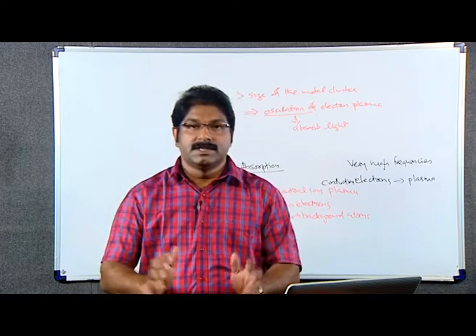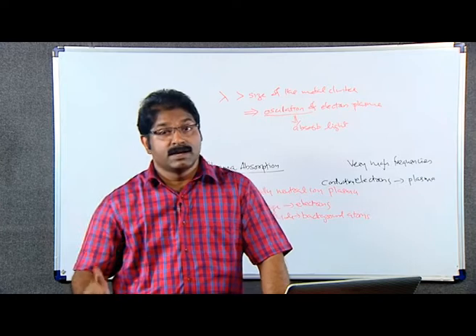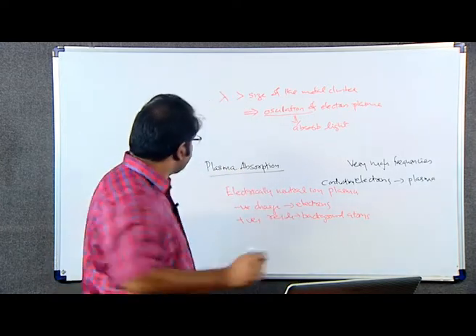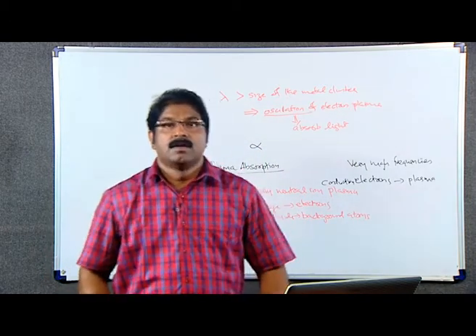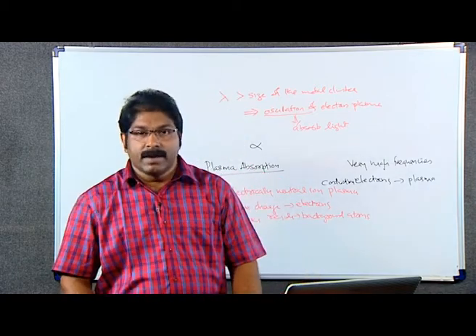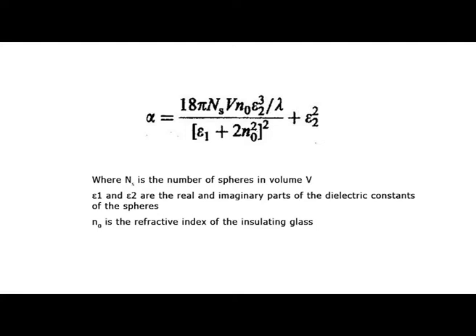The absorption coefficient of the material for different wavelengths can be expressed by a theory developed by Mie. The absorption coefficient alpha is given by alpha equal to 18 pi ns V n0 epsilon 2 cubed divided by lambda, times the whole divided by (epsilon 1 plus 2 n0 squared) the whole squared plus epsilon 2 squared, where ns is the number of spheres in volume V. Epsilon 1 and epsilon 2 are the real and imaginary parts of the dielectric constant of the spheres, and n0 is the refractive index of the insulating glass.